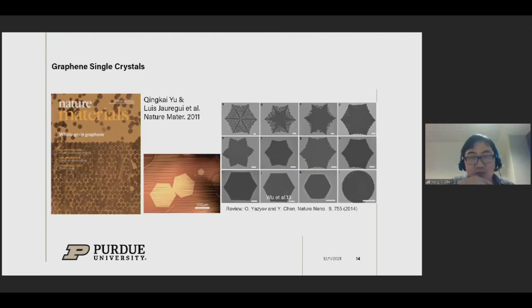A few years later, after we made these very large graphene sheets, which are polycrystalline, by the way, the next frontier was how to make very good quality single crystal graphene. And we tried with Qingkai. Again, we developed somewhat controlled seed growth of these single crystals, by growing at a much lower rate or stopping the growth earlier than what I showed for the large-size graphene film. And we can also use graphitic seeds to create nice, beautiful arrays of single crystals.